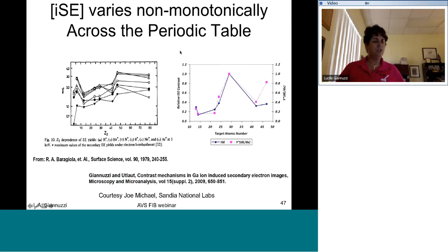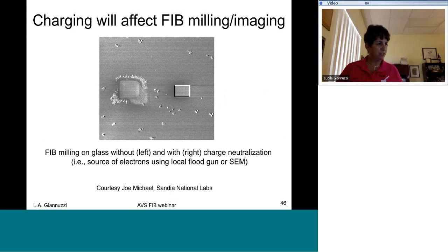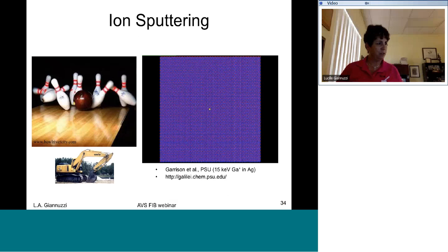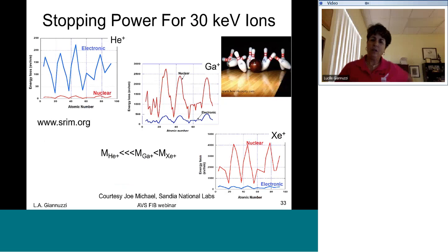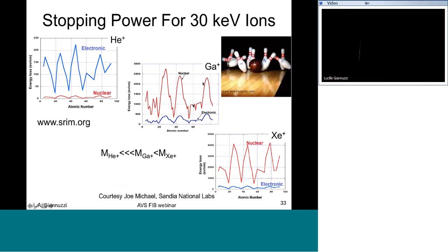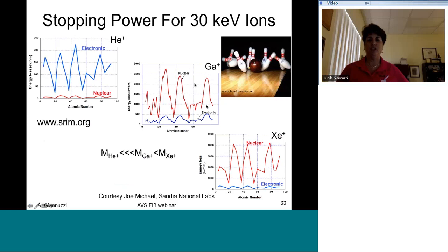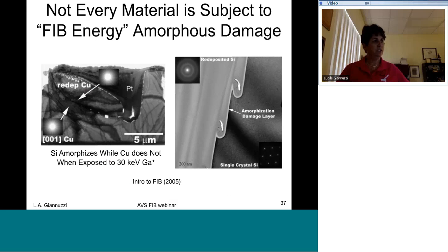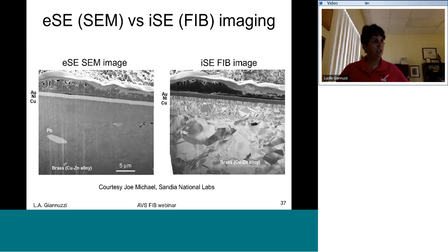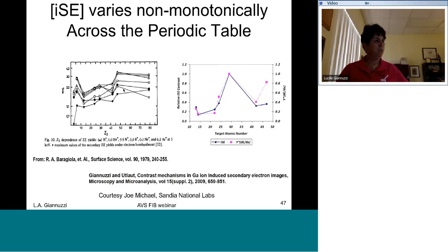We saw that also with the sputtering. So let me just go back a sec and show you this, because I didn't really point this out. Here we go. You see, with the sputtering, you see these peaks and valleys, and these peaks and valleys are due to the D-shell filling in the periodic table. And what you also see, if you look at the ion-induced secondary electron imaging, is that you get similar types of peaks and valleys across the periodic table.